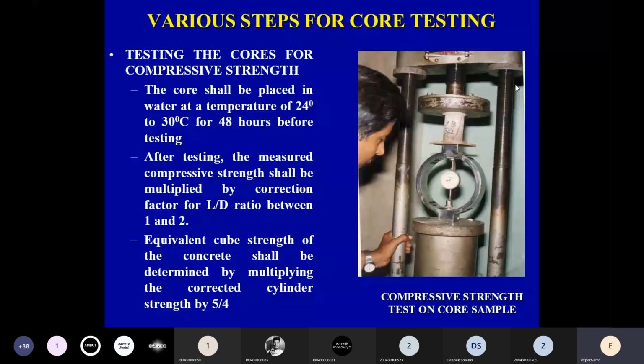But currently the Indian code IS 456-2000 is under revision. So we are working on the revision of that. And this correction factor of 1.25 is till now only valid for concrete grade up to M55. So once you move on from M55 to M100, these correction factors are different. We have done the testing in our lab and we have already submitted the data to the Bureau of Indian Standards, which is already approved. So just to give you an example, for M100 grade concrete, this correction factor will be 1.15.